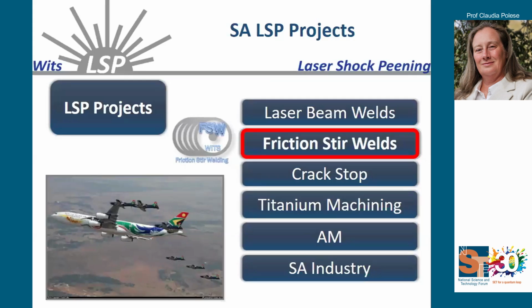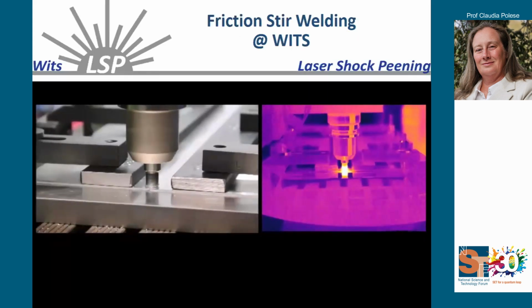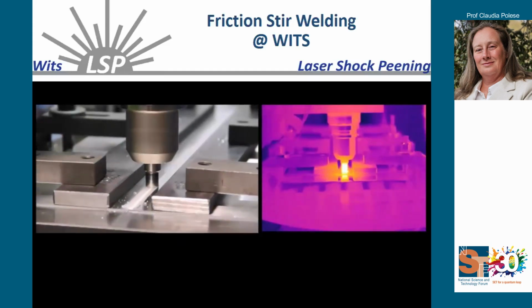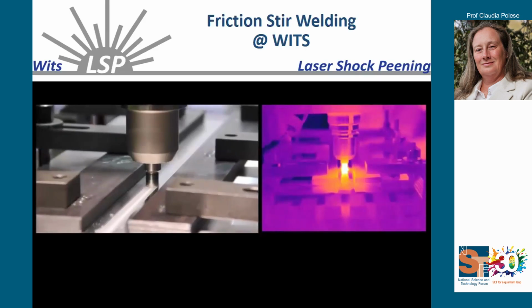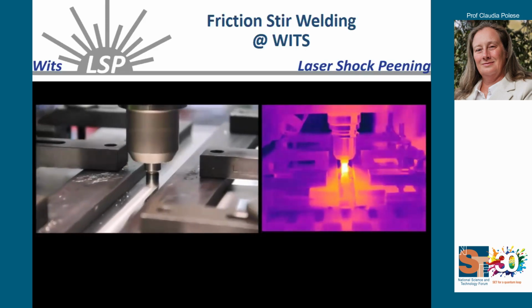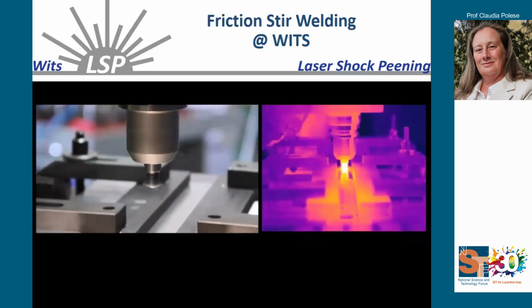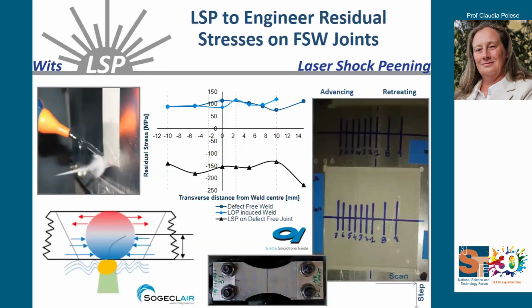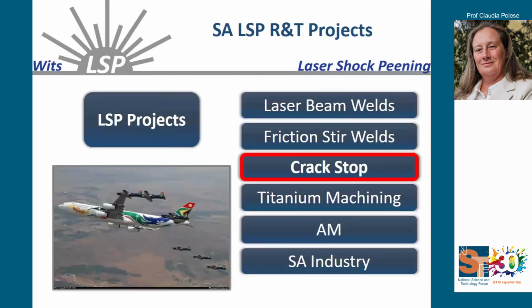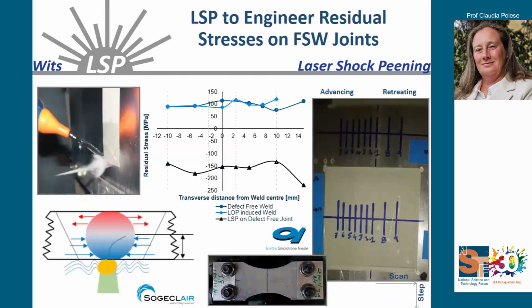Same thing was applied to other types of joints, for example friction stir welding, which is what we call a solid state process. This was actually the technology I used for my PhD, so I can bore you to death on this. It's a fantastic process because it really has minimum defects. There is always the possibility of a small imperfection at the back of the weld. So even here, with another colleague from Germany, we try to target just the back of the component to see, even if there are small cracks or imperfections, or equally lack of penetration, whether we can reverse the process. And we got a very, very nice result as well.